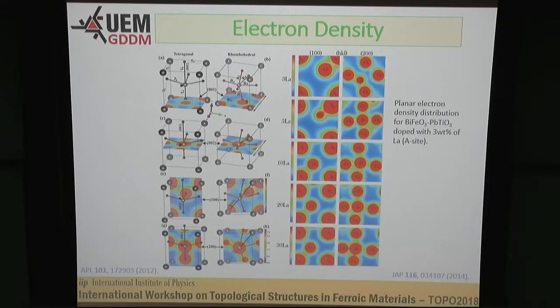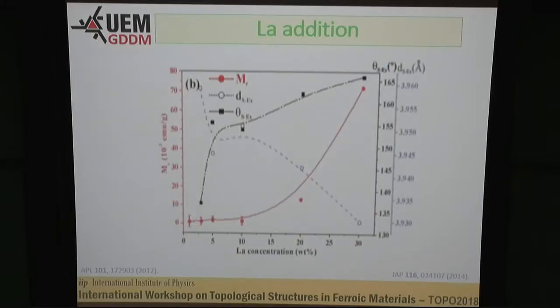As we have all positions refined by Rietveld refinement using X-ray and neutron diffraction, you can do the simulations and see how the structure is tilted to accommodate these positions in the samples. And this, please forgive me because this is not a good image, but with lanthanum concentration, the magnetization increases, the distance for superexchange in the magnetic interaction decreases in this case, and the superexchange angle increases with increasing lanthanum.